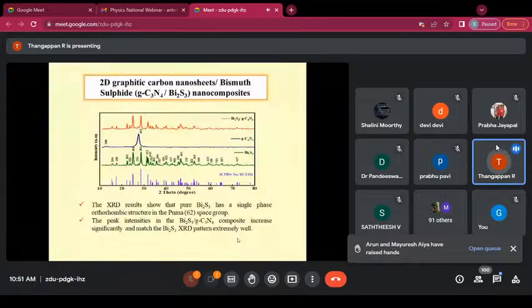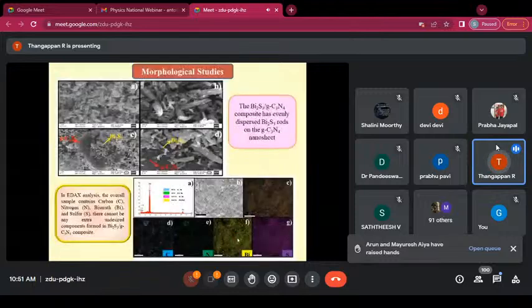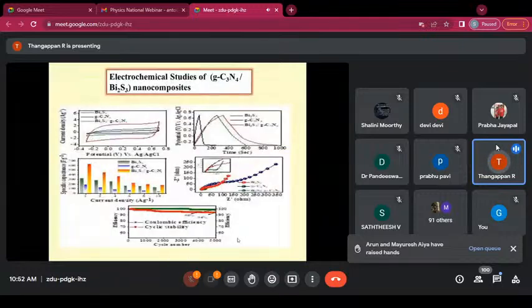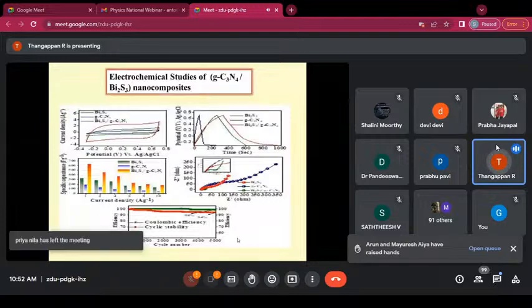We have also done a graphitic carbon with bismuth sulfide nanocomposite for supercapacitor application. Here nanorods are formed on the surface of the graphene sheets, and in EDAX mapping we have seen that bismuth, carbon, and sulfur are present in the composite sample. We studied the three-electrode system, and the efficiency and stability of the material are very high. The capacitance is also very high for bismuth sulfide, 650 farad per gram at 1 ampere per gram current density. Efficiency is also very high, above 97%.